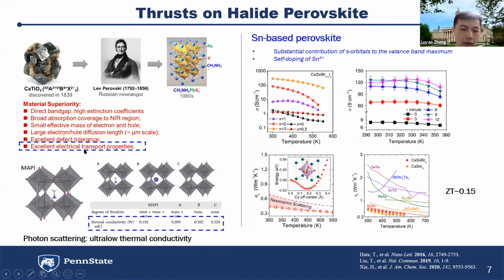We have very good electrical transport properties inside this halide perovskite. This material basically has an ABX3 structure. As shown here, we have methylammonium here, and the metal, usually lead or tin, and also halide on this side. And recently, people found that this structure is kind of unique in having phonon scattering inside the material, resulting in very low lattice thermal conductivity. These two features are pretty good for high performance thermoelectric materials. But for this lead-based perovskite, they found the electrical conductivity of the intrinsic lead perovskite is very low.